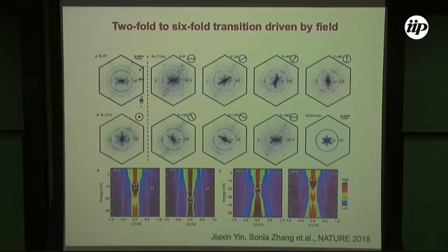You can see the Kagome magnet has a 6-fold symmetry lattice, right? So then your electronic structure should be 6-fold. But what we see, since the time is short, is that it has a 2-fold symmetry. So that reminds you of some sort of nematic order. And nematic order is not new. It has been seen in superconductors or other correlated electron systems. It's a signature of strong correlation.